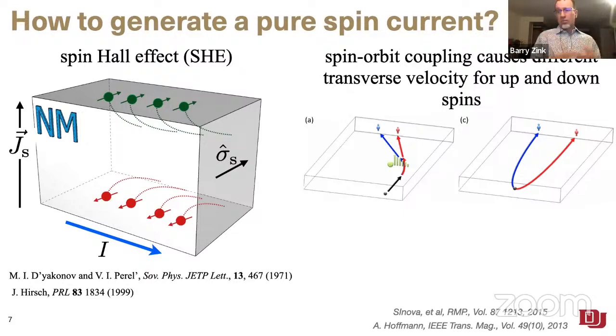And that spin Hall effect, we're imagining we have a bulk chunk of a metal with spin orbit coupling. And if we drive a current through that, we're of course launching a flow of electrons. And in this little cartoon, the electrons would be going from right to left through my chunk of this, say, platinum, which is by far the most common choice. And the transverse velocity that the spin orbit coupling gives to the different spin species makes this up or right spins go up and the left spins go down. And so we've separated those spins by their angular momentum state.